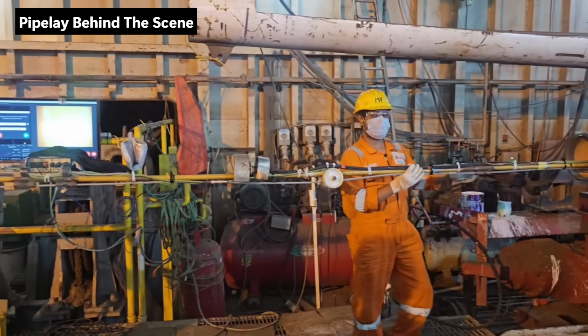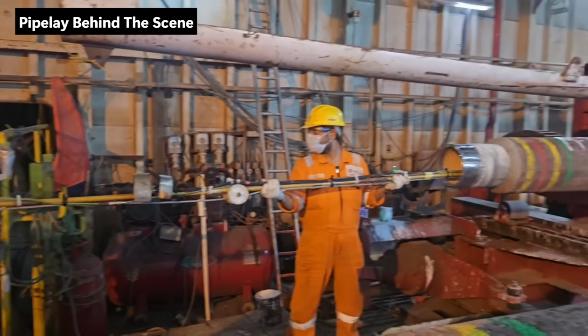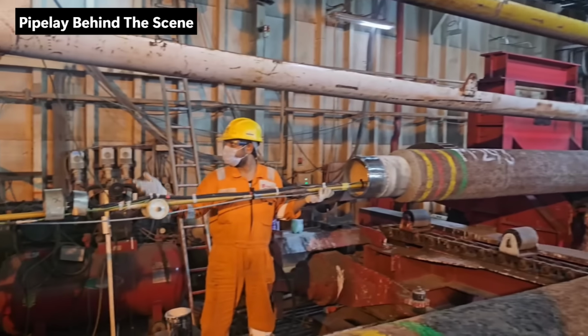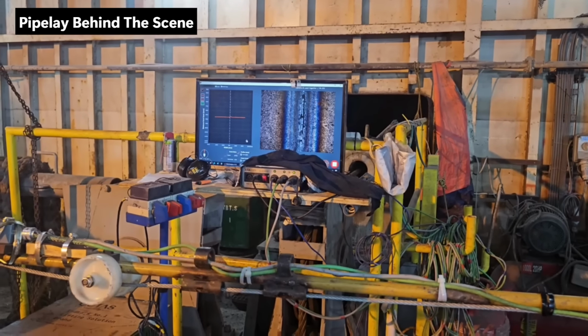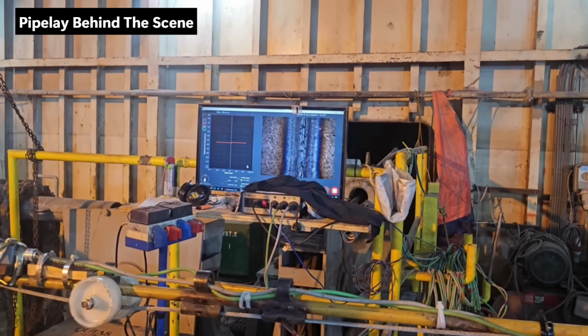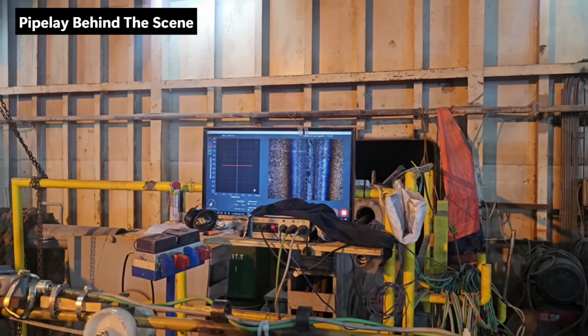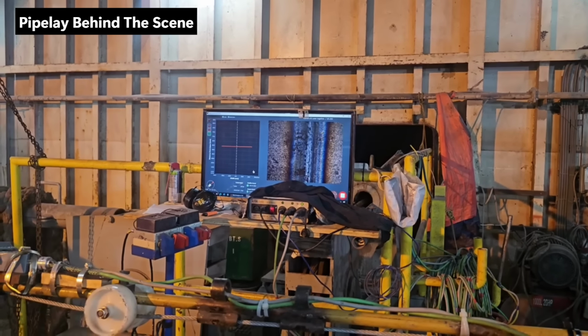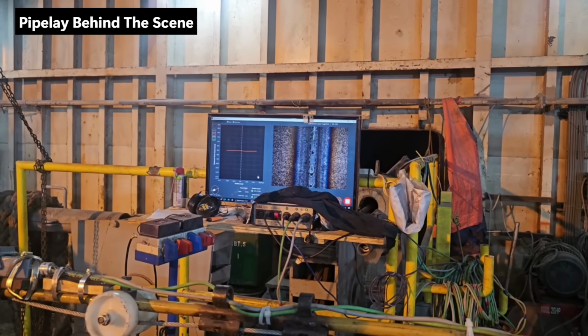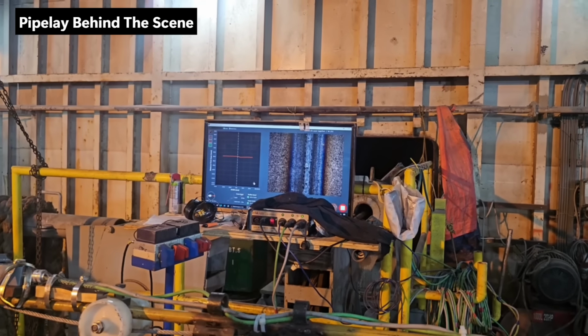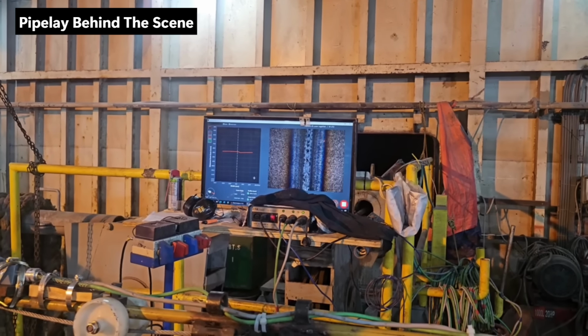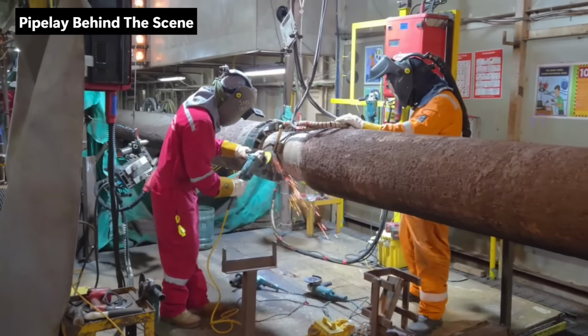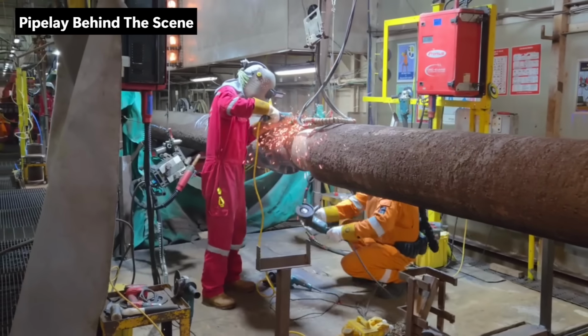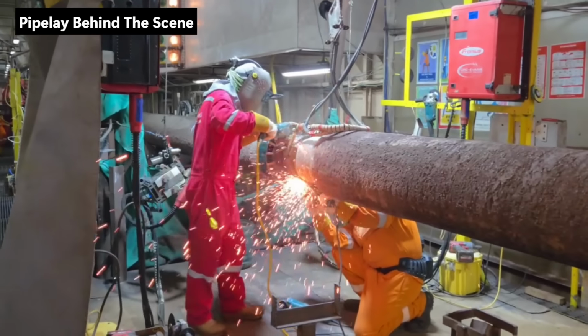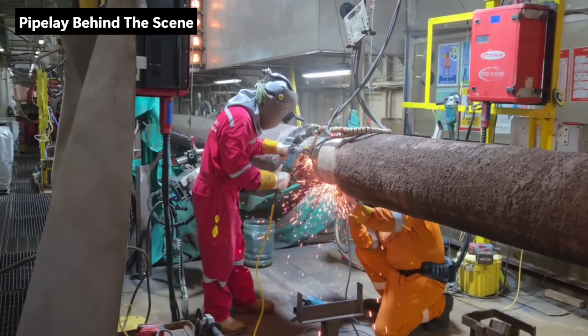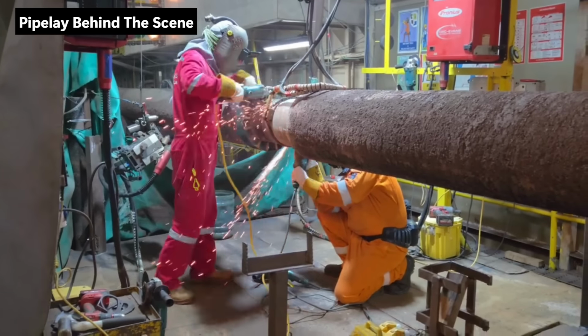Here is something interesting happening. An ultrasonic probe is being moved across the weld. This is checking for slag, small pockets of non-metallic material that can get trapped inside the weld metal during welding. You cannot see slag from outside. It hides inside the weld, but it weakens the joint. If a problem is found at this stage, the work stops. The joint is cut out, and you start again from the beginning. This is standard. There is no negotiation on weld quality in this industry.